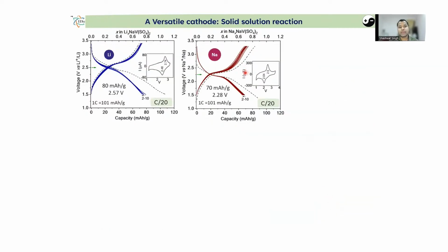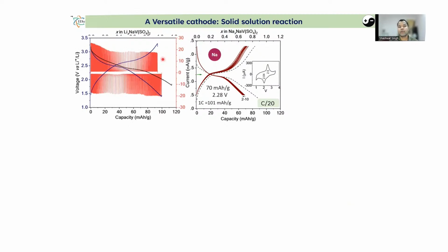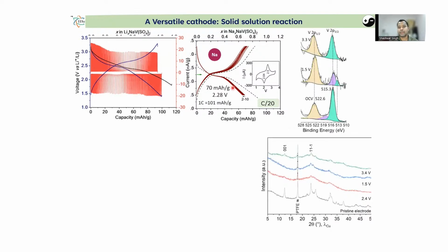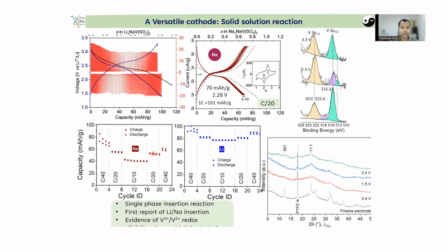Through electrochemistry, we were able to prove the one electron reaction. However, the second electron reaction couldn't be achieved because of electrolyte stability. But for the one electron, we see that it follows a solid solution reaction, both for lithium as well as sodium ion, proving its versatility. However, rate kinetics is lower for sodium compared to lithium. From PITT-based data analysis, we see a classical current relaxation behavior, proving that the reaction mechanism is a solid solution reaction. This is again supported by ex situ XRD-based analysis, as well as the presence of vanadium as the redox center with ex situ XPS-based analysis. And further, the rate kinetics is slower for sodium compared to lithium, which could be because of the bigger size of sodium.